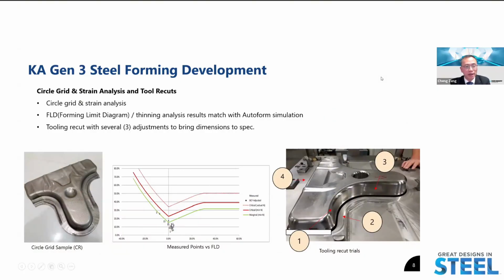Also, we did the so-called grid analysis, a strain analysis, to try to see where the material deformation could start, as well as what the future hotspot areas could be and what the formability looks like, where the material goes. And then we improved our tools at the field locations. You see some where we dropped our angles, some where we overbent in order to get the dimension under spec, and some where we added some material in order to bring the wall to nominal. Okay, and also the flange geometry had small changes in order to get the dimension to spec.